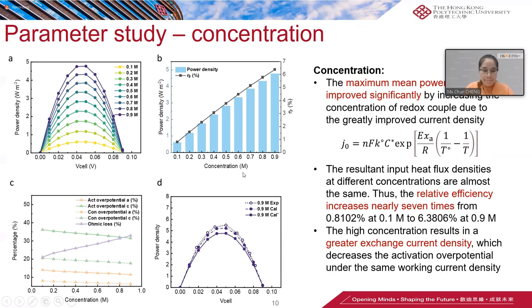Also, assuming that the thermal conductivity and heat capacity are independent of the electrolyte concentration, the resultant input heat flux densities at different concentrations are almost the same, right? Thus, the relative efficiency increases. At the same time, the high concentration results in a greater exchange current density, which decreases the activation overpotential under the same working current density. This effect can be seen in figure C.